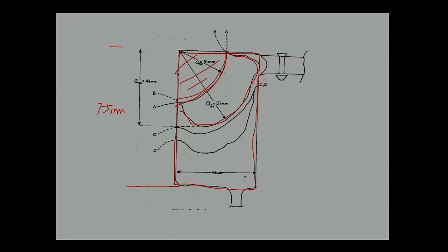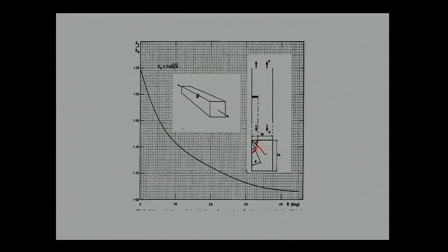So there are two deviations from what that table showed, that graph showed. One is your cross section is rectangular. The second thing is the crack length is much larger. In terms of ratio, it is about 50% of the width instead of 20%. So how to comment? In order to use this, obviously you need to compensate for those differences.